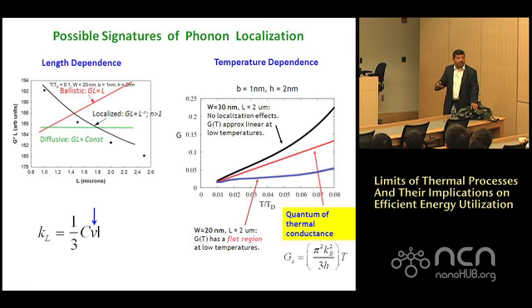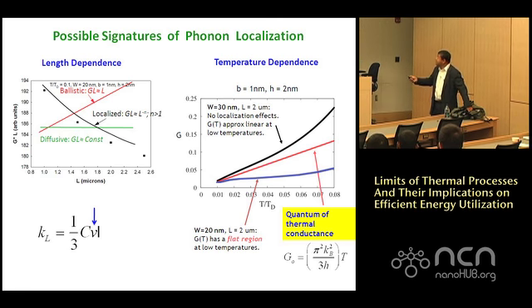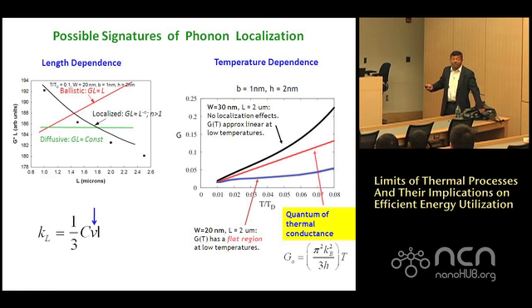Just like you have a quantum of electrical conductance, the quantum of thermal conductance is pi squared k_B squared over 3h multiplied by T. It's linear with T. And this quantum has been shown. There was a beautiful experiment done at Caltech by Roukes and Schwab, where they showed this quantum of phonon conductance, which is independent of all material parameters and only depends on the physical constants, down in the millikelvin temperature range. If this is true, then only the fundamental modes should travel, and you'll be able to see it at much higher temperatures as well. So this is the experiment that we are trying in my lab right now, to see whether we can get these length and temperature dependences.